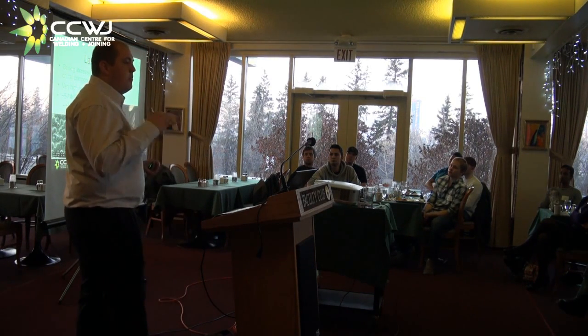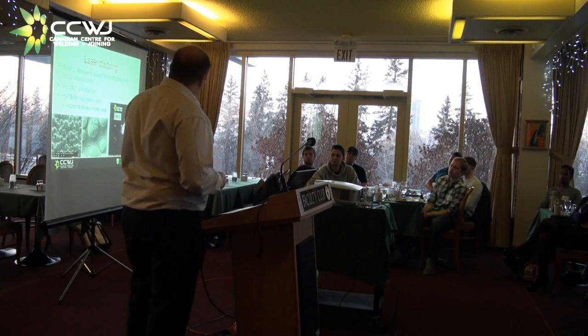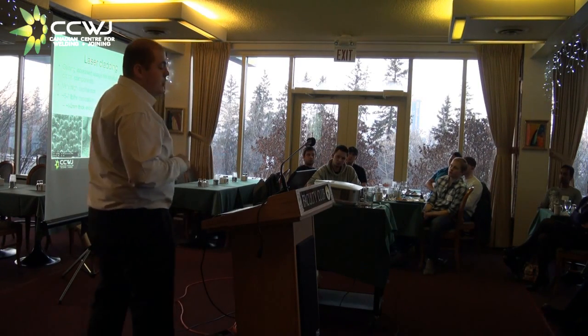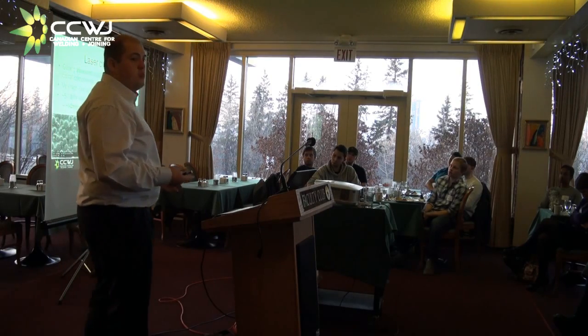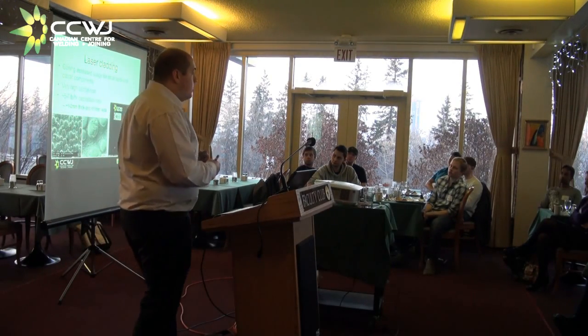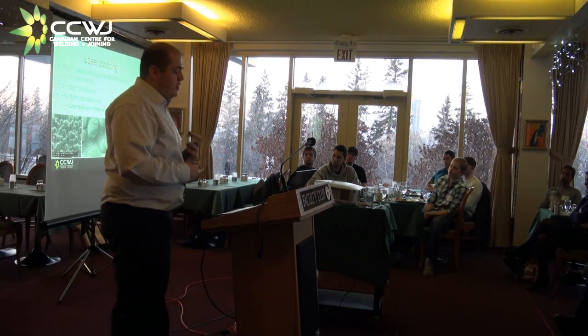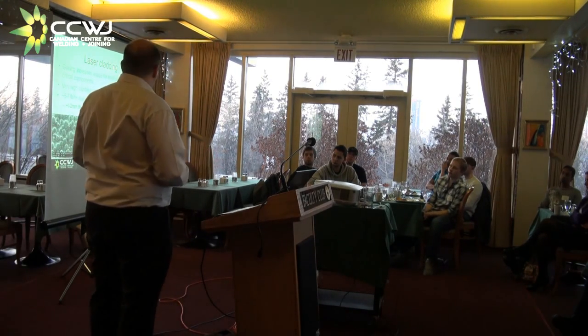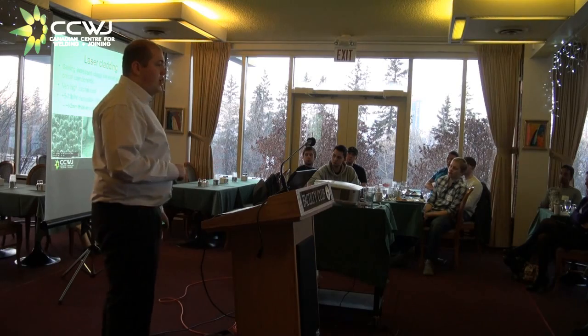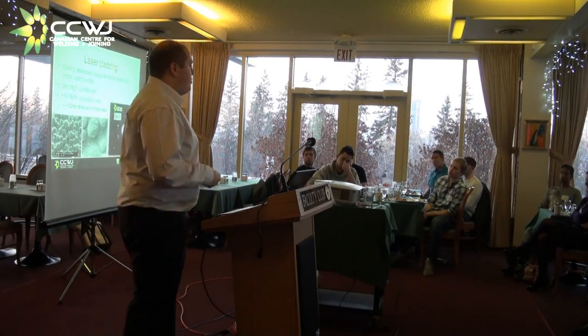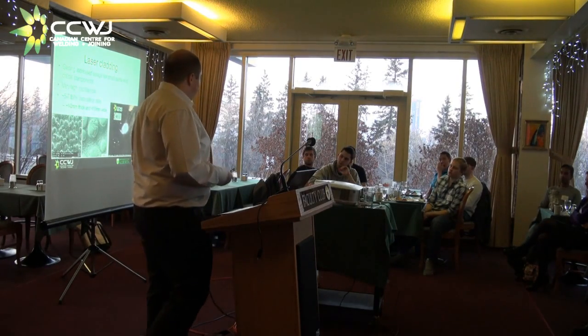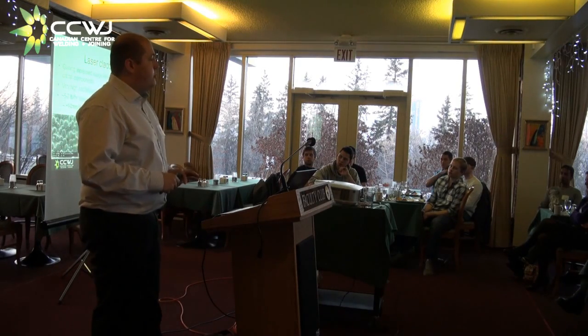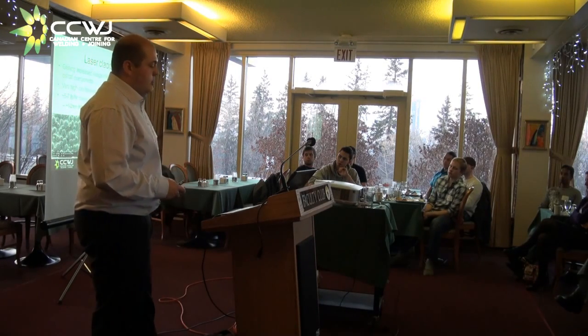where fusion and penetration can be an issue, say, on downhole drilling tools. It still uses a powder consumable, so within the powder is our nickel matrix and our tungsten carbides. A characteristic of it is that it produces very high fraction overlays, but it is also very costly. It's a lot of capital expense for a company to get in the game and start producing these, especially since there are very few people that actually have direct experience with a laser system.